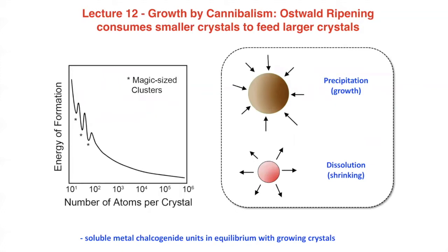When you have small and large particles together in a mixture, the small ones are more soluble. They break into pieces. The big ones are less soluble. And this is something the Gibbs-Thomson relationship has laid out for you. And so the small ones fall apart while the big ones grow. And this gives rise to Ostwald ripening, right? Freezer burn on your ice cream being a good example.